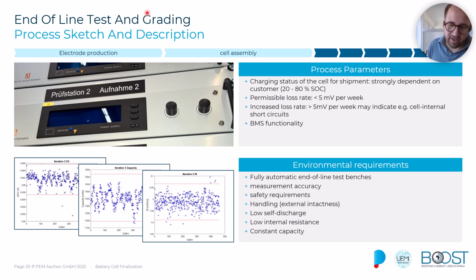Typically, there's then a grading happening. They classify the cells into different classes, for example, 3 or 10 classes. A grade A cell might be 100 to 105% of the nominal capacity and a low resistance, a grade B cell around 95 to 100%, and a capacity at specification or slightly higher.